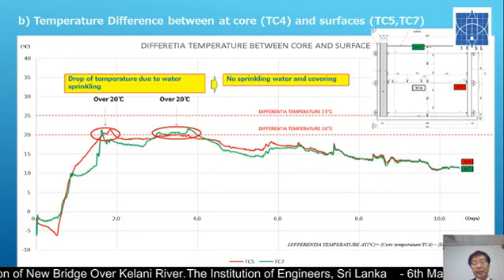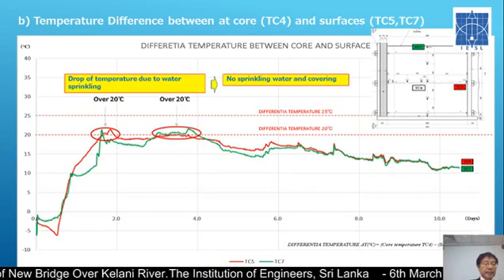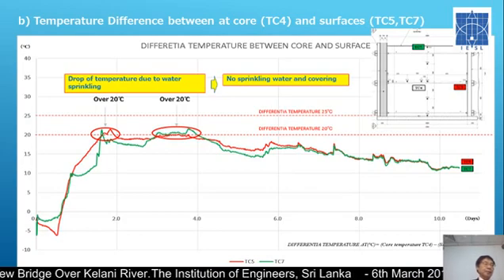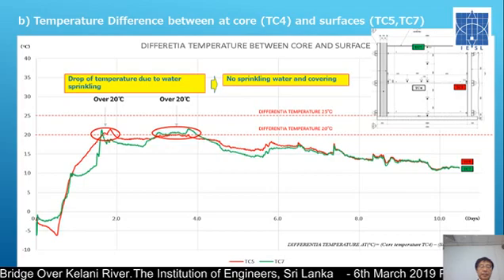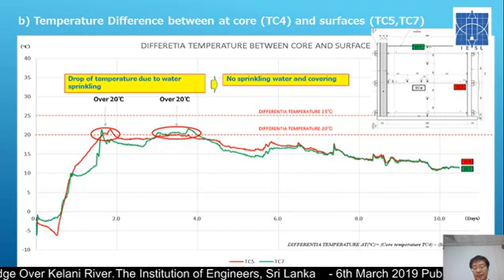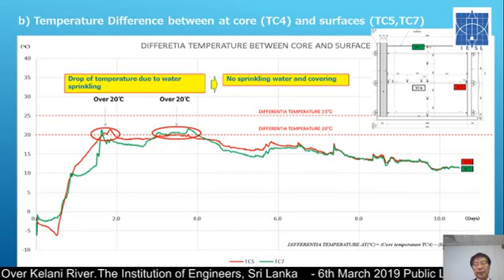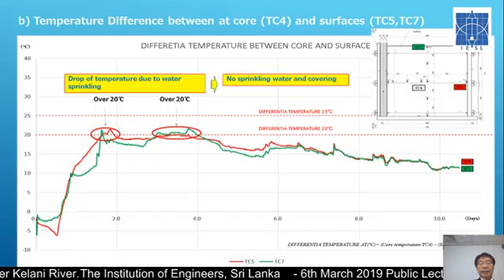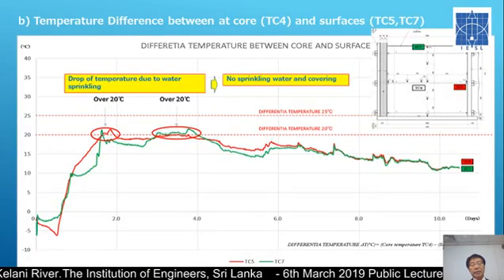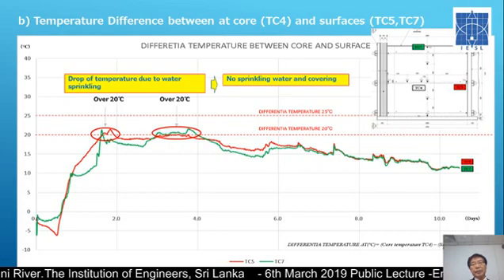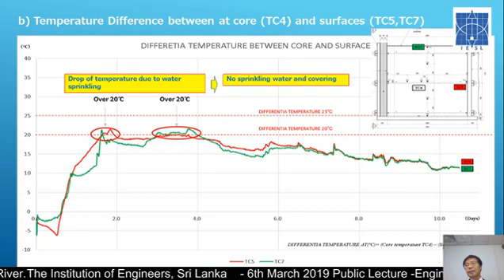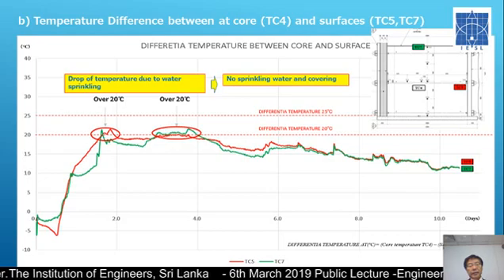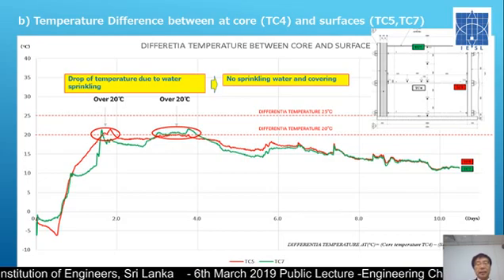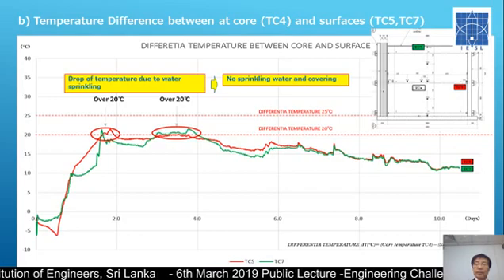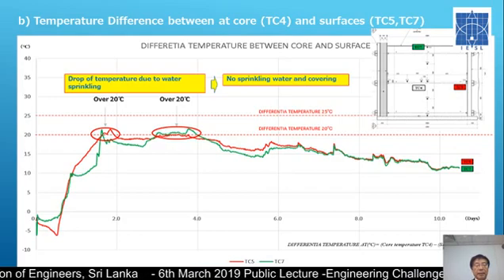And we consulted with the professor, and we stopped it. Spraying the cold water on top of the surface is not useful, because it makes a higher temperature difference. So we have learned from this that controlling the temperature of the fresh concrete to be cast at the site is very important, and at 25 degrees, we can probably succeed in the actual construction. And for the temperature difference, we have to give more careful consideration to the curing.